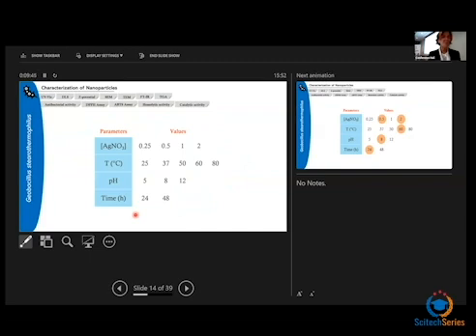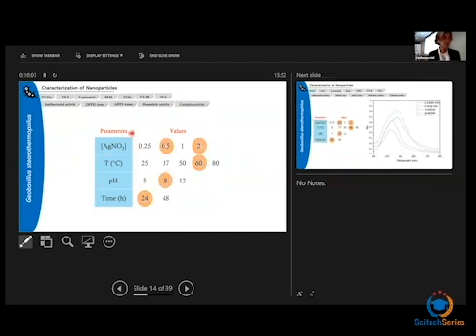To determine the optimal conditions for nanoparticle formation, we evaluated the effect of various parameters, such as silver nitrate concentration, temperature, pH, and time. The synthesis resulted to be more efficient at 60 degrees centigrade, at pH 8, and with an incubation time of 24 hours. We also assessed that the best conditions were using 0.5 and 2 millimolar silver nitrate as the precursor.